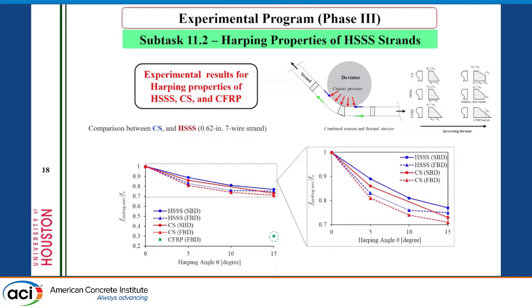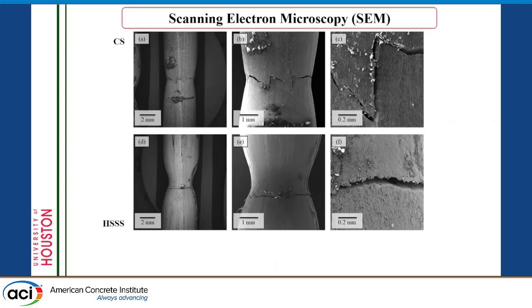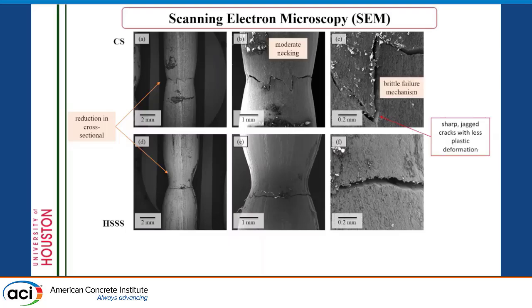So what we try to do is to understand why this is happening, since this one has lower ductility, so why we got results similar to the carbon steel. So we went further to understand. We took the center wire from the strand for each carbon and stainless steel, and we did a uniaxial test just to see. You can see the ones on the top are the carbon steel, and the ones on the bottom are the stainless steel. You see the reduction in cross section for the stainless steel is higher than the carbon steel, and it has more localized strain. Even the failure shows more brittle for the carbon steel compared to the stainless steel.